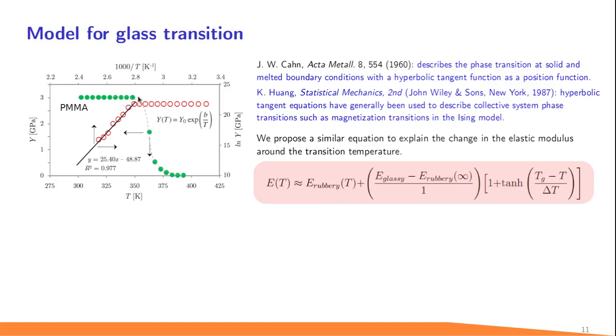to 345 Kelvin, and above that the elastic modulus dropped rapidly to 1.7 GPa and down to 0.5 GPa at 368 Kelvin. And at the highest measurement temperature, the elastic modulus is around 8.9 MPa. And we find here that the reduction in elastic modulus when the temperature changes from the glassy plateau to the rubbery plateau is around 2.5 orders of magnitude. This is very close to the most accepted value of around 3 orders of magnitude, to mention that the dropping region is the glass transition region.